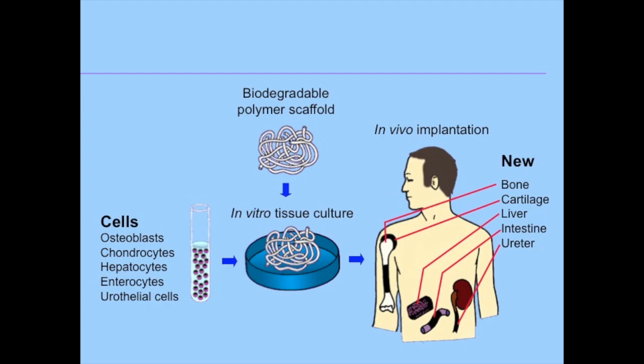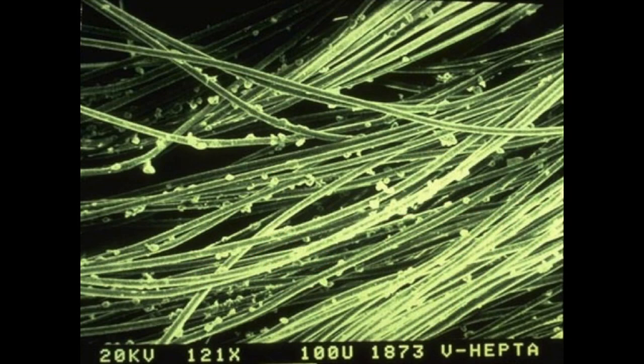What Jay and I did was create three-dimensional polymer scaffolds where the cells could be close enough together to reform structures. Also, the way you grow the cells is very important — it's not just simple tissue culture. You have to have the right stresses to make them grow in the right way, and then you could make the tissue. We converted these into scaffolds with fibers and cells. Prasad Shastri, one of my postdocs who now runs a big institute in Germany, worked out a way using CAD-CAM techniques to make these into virtually any shape, using three-dimensional printing or various foam techniques.